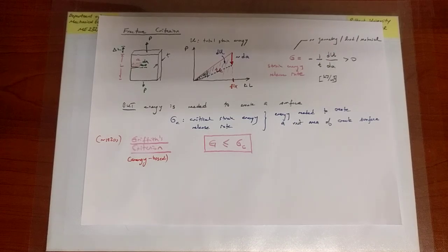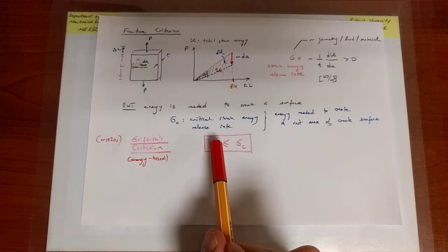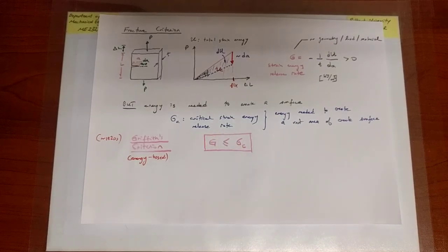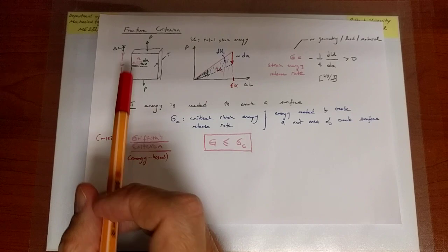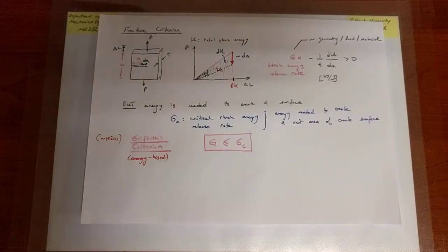And what you can also recall at this point is eventually when G is equal to GC, in our experiments, the physics was a little bit different. The process was rather slow at the beginning, but ultimately remember that the failure is catastrophic. It all of a sudden propagates and the tape just peels off before the whole interface has failed. At some point, the crack propagates very rapidly and just peels the tape off, or in this case, will crack through this structure. All right.